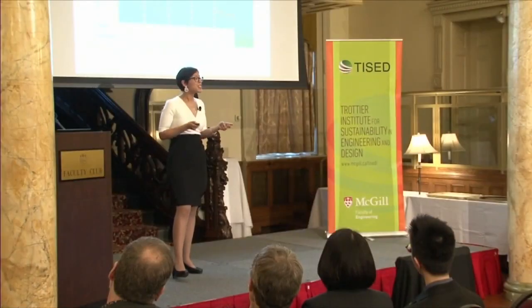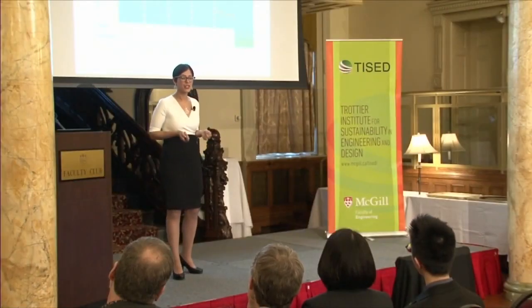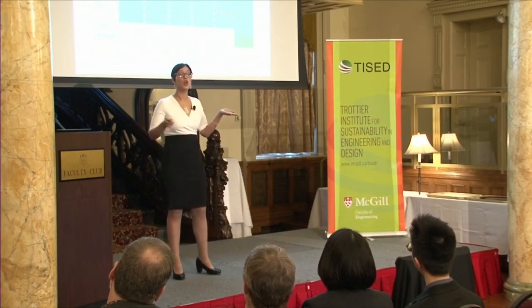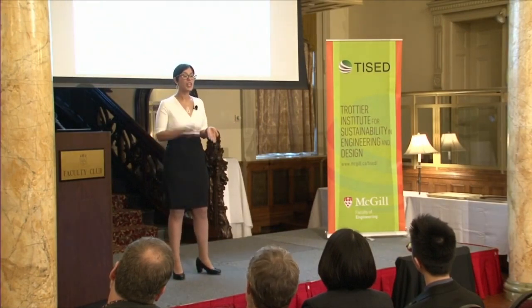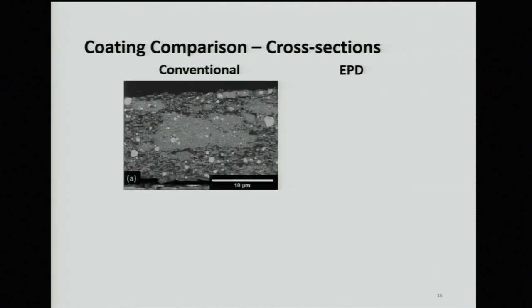And the difference between these two was the way that we made the electrodes. So we took these electrodes, or the coatings, we cut them in half, and we imaged the cross-section. So up here, I have a scanning electron microscope image of the cross-section of the conventional coating along the thickness. And the first thing you might notice is this chunk in the middle. What is it? You see, we have 3 different types of materials, right? We have the lithium titanate, we have a carbon, and we have a binder. So how can we know what this is?